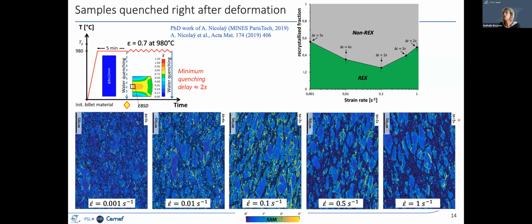In these experiments, the strain rate varies. And these are the recrystallized fraction we can measure in these deformed and quenched samples. These data include both dynamic and post-dynamic recrystallization. If we analyze the dependence of recrystallization kinetics or recrystallization fraction as a function of strain rate, it seems that the dynamic recrystallization is first going slower and slower, and then faster and faster, which is a bit surprising, but this is the result which is always reported in the literature.